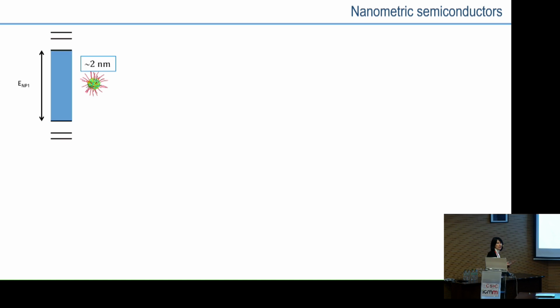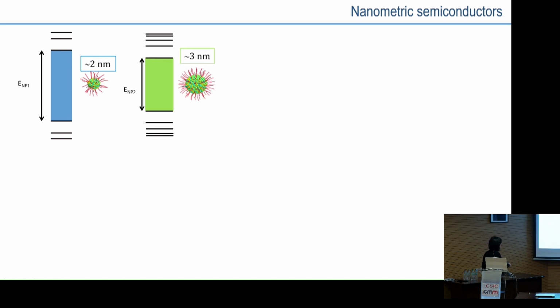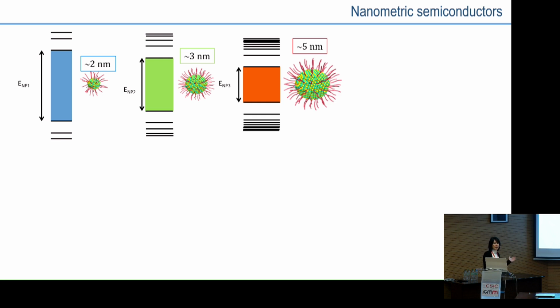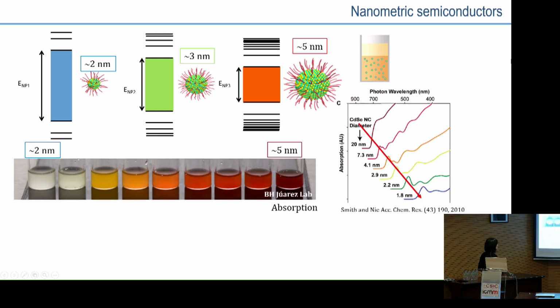So in this way, as an example, for cadmium selenide nanoparticles, if we have particles of around 2 nanometers, let's say, we can have a band gap in the blue. As soon as we increase the size, of course, we will get behaviors closer to the bulk material. And when we have these particles dispersed in a liquid, so we have a colloid, what we observe with our own eyes is the change in color depending on the nanocrystal average size in these solutions, ranging from 2 nanometers, here the vial on the left, to 5 nanometers, here the vial on the right.